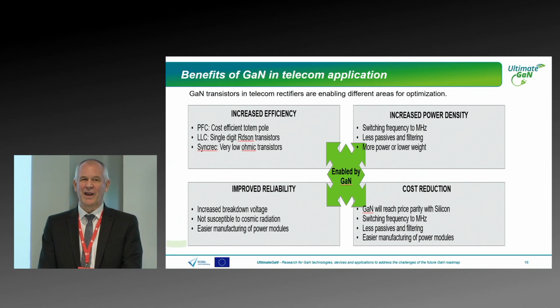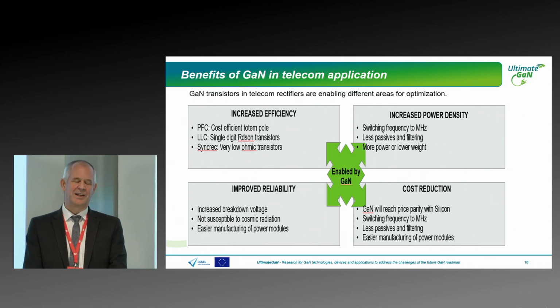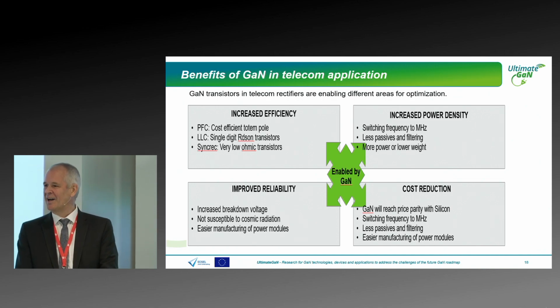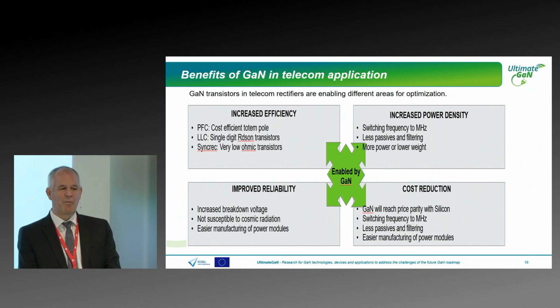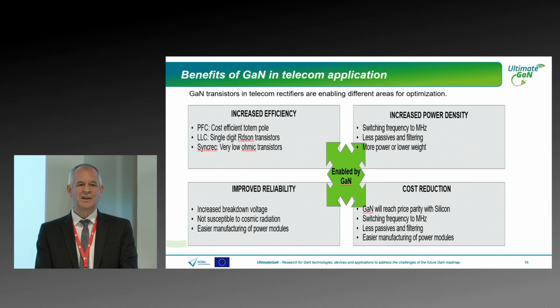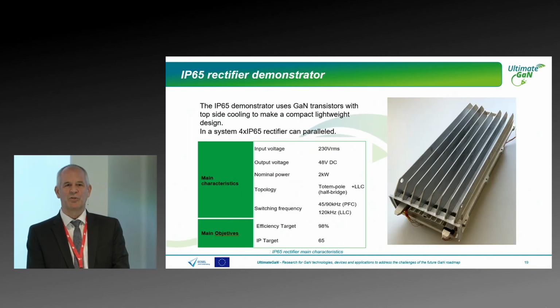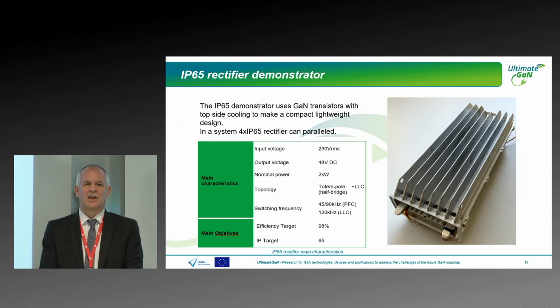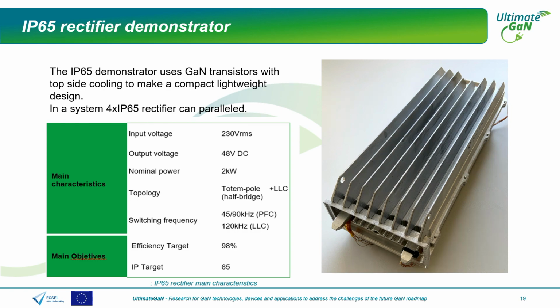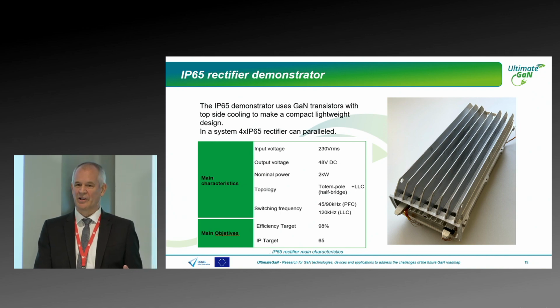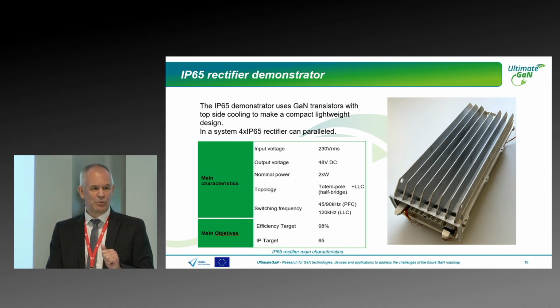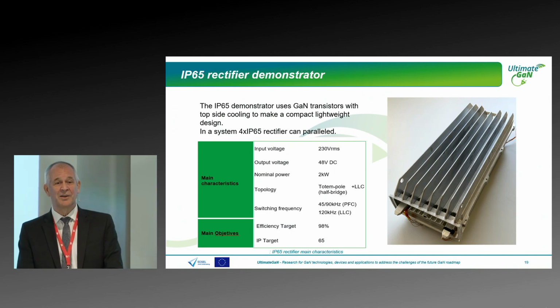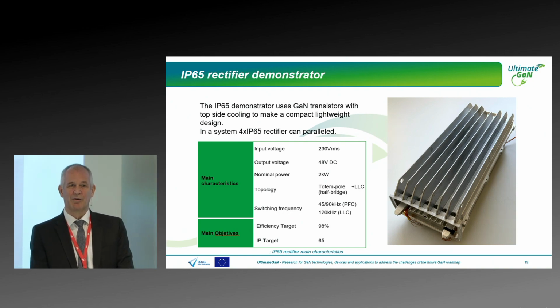Yes, the benefits of gallium nitride in telecom applications. LTEC is the second time a partner with us in these projects, and they are making really good stuff, using gallium nitride in a proper way. And this is what they did this time. And if you look, yes, efficiency target, 98%. Maybe not perfect for a paper, but excellent for a product. They had even more. So they were over 98, but they decided out of economical reasons to stay with the 97.9. But this is what we have to do in reality, to find the point where it matches the market with the efficiency. And somebody has to pay for gallium nitride.